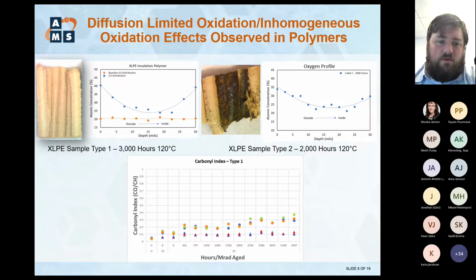The types of DLO things, these are basically some of the DLO results and the things we're doing to understand and basically account for the impact of DLO. So diffusion limit oxidation, as was mentioned earlier in the day, is basically the insulation material will consume the free oxygen that's available for diffusion at its surfaces, and it'll prevent it from penetrating, and it won't be able to diffuse to the interior surface. So you'll end up with degraded surfaces of the insulation, but relatively non-degraded, non-oxidized material toward the middle of the material. So what we see here are profiles.